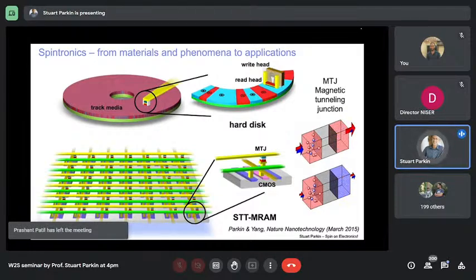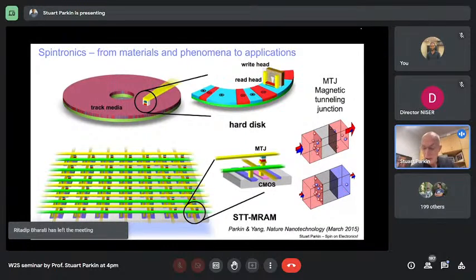I'm going to come back to that later, but I invented something I called a synthetic antiferromagnet, and this is critically important to building both spin valves and magnetic tunnel junction sensors and memory elements. You have to eliminate all the stray fields from one of these layers. And you can do that by creating an artificial antiferromagnetic layer using an oscillatory long-range coupling that I found was common to nearly all the transition metals in the periodic table. And typically one uses an ultra-thin layer of ruthenium to create a very, very large antiferromagnetic coupling and a synthetic antiferromagnet. We'll come back to that briefly later.